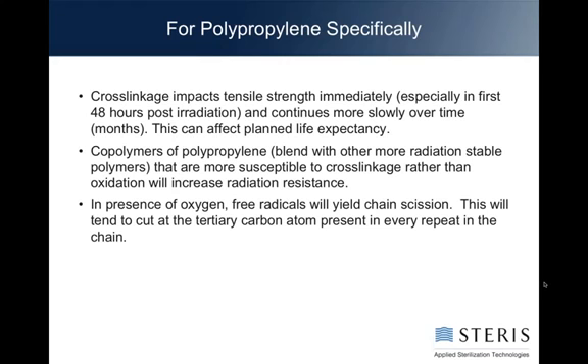In the presence of oxygen, though, polypropylene will also create scission events, as a result of the free radicals it created during the irradiation process, that will yield chain breakage. This will tend to cut specifically at that tertiary carbon present in every one of those repeat segments on that structure.